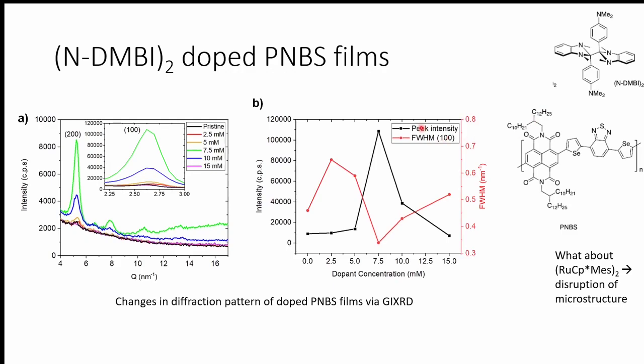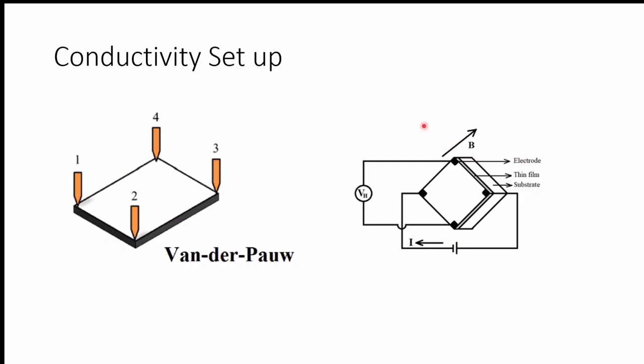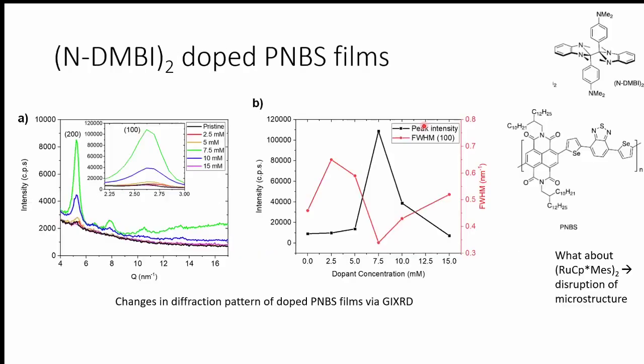But if it's an ion, it will not be as easy to phase separate from one another because of the Coulombic binding. Now, the next thing was to measure the conductivity. How is the conductivity changing? But before I get into that, I forgot to mention what is happening to the ruthenium doped one. Since the N-DMBI had no reaction, I did not study it further. As for the ruthenium dimer, the moment you dip your polymer film in a very low molarity ruthenium dimer, the diffraction pattern you had kind of vanishes, and you just see air scattering.